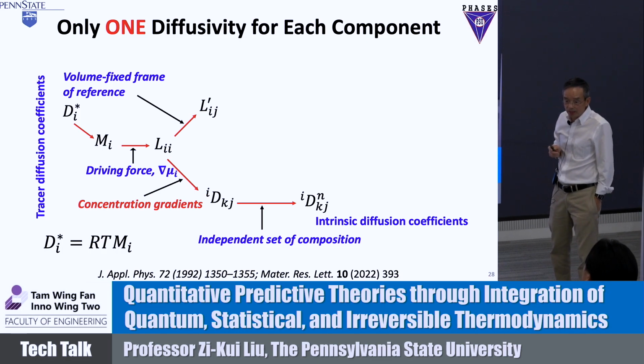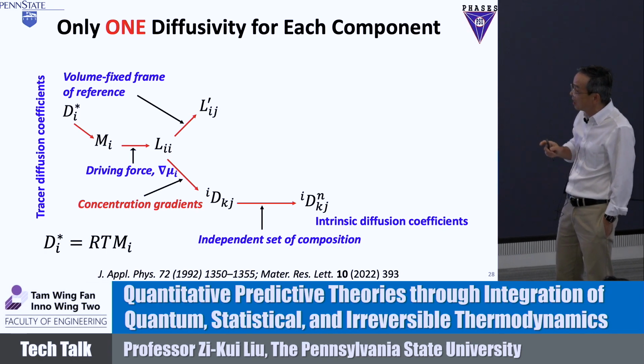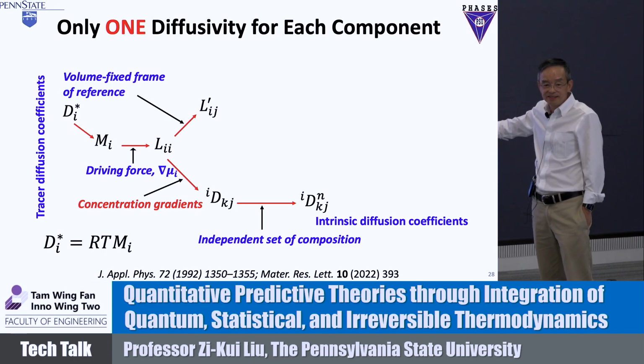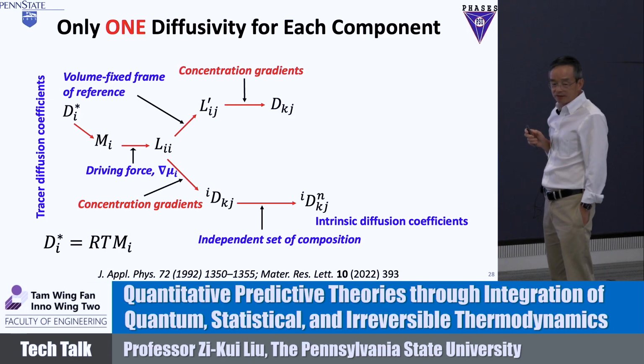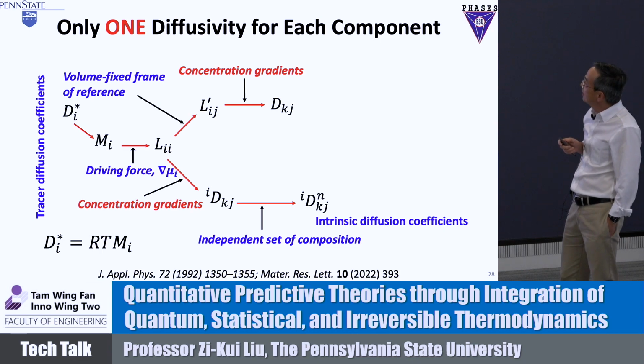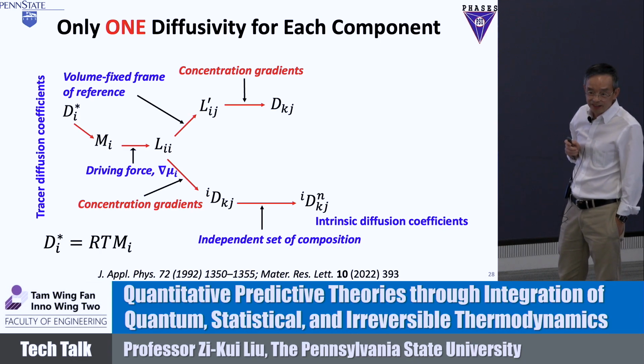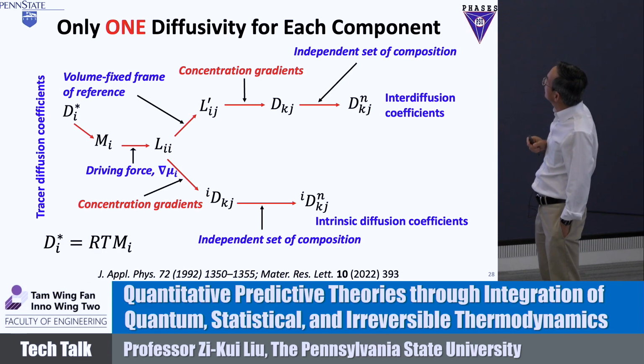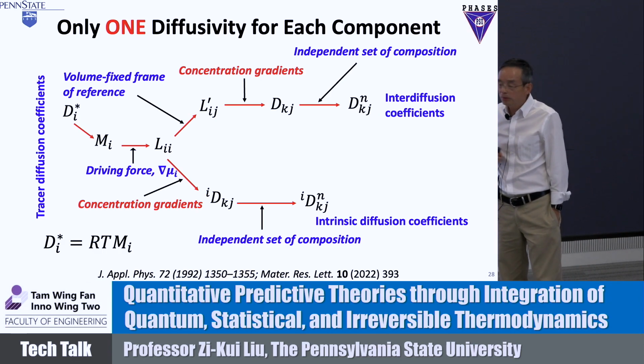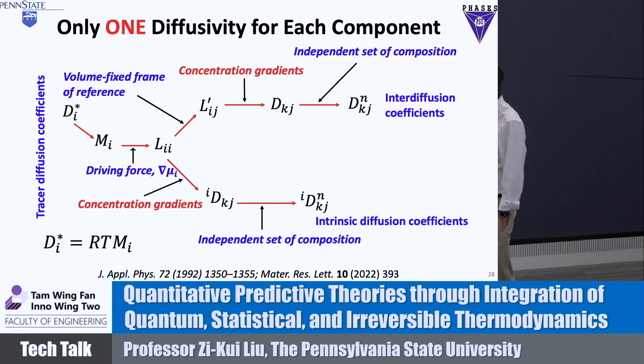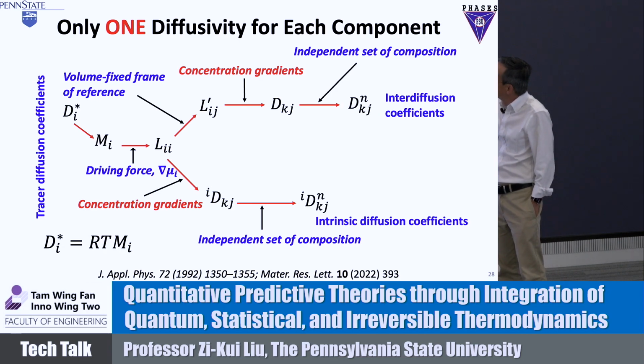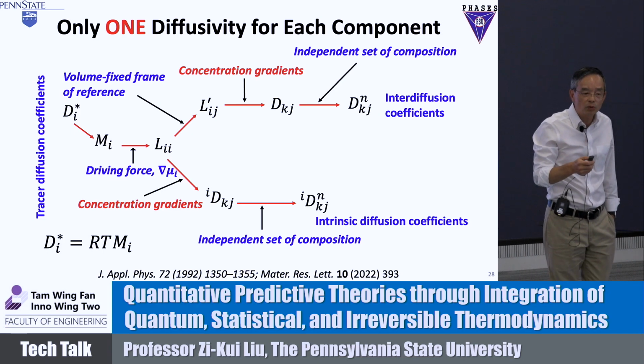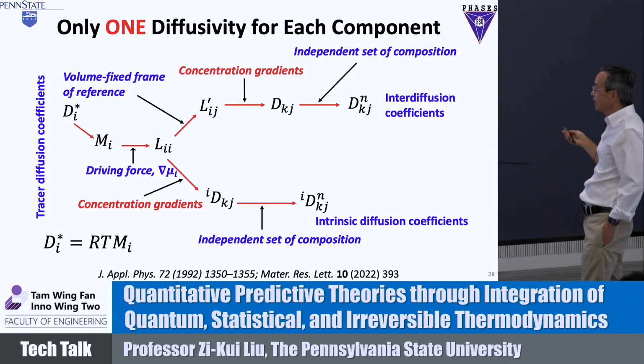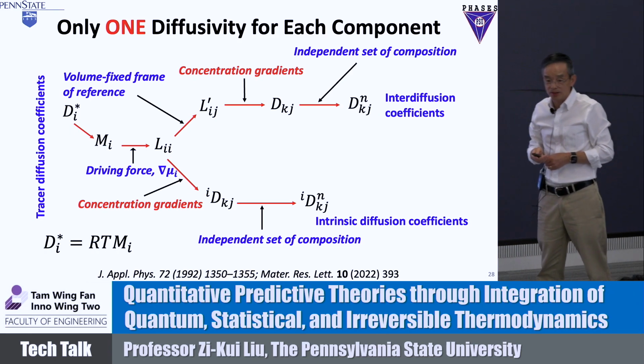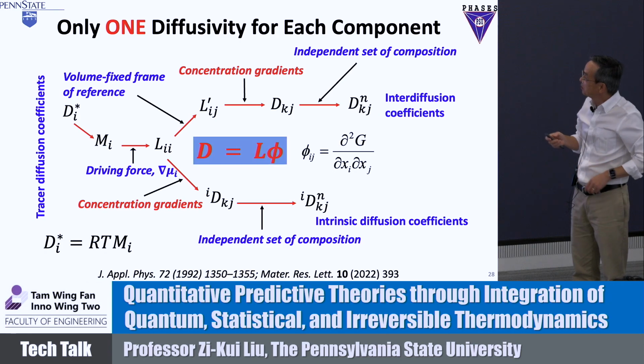But you still use the chemical potential gradient. Now it's not only the chemical potential of the diffusing species, but the chemical potentials of all species, so it's a matrix. And you can change this to composition. From the chemical potential to composition, you get the chemical diffusivity matrix. Then you remove the independent one, and you get the typical interdiffusion coefficient. So we have mobility, or tracer diffusivity, we have the intrinsic diffusivity, and we have the interdiffusion coefficient. And these three sets are matrices, while that one is a single variable. So what's the connection between all these diffusivities? That's what my professor did in 1982 in his PhD thesis. It's the thermodynamic factor.